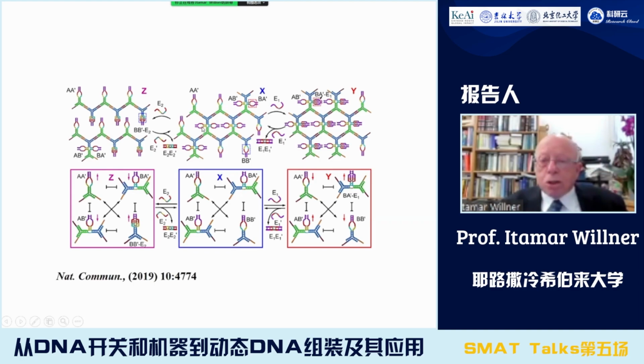How can we control the stiffness? If we add a strand, for example, E prime, and this E prime stabilizes the biloop region of the double bridged units, we stabilize these units, we will increase in the equilibrium the cross-linking components, and we will get a higher cross-linked hydrogel.